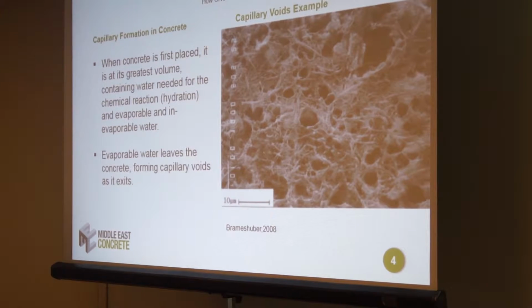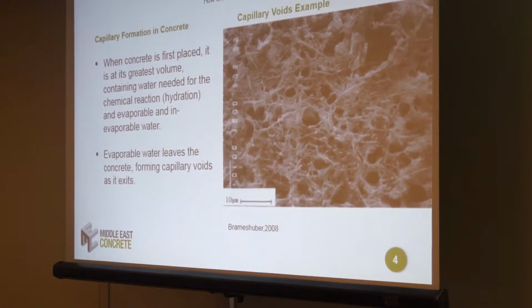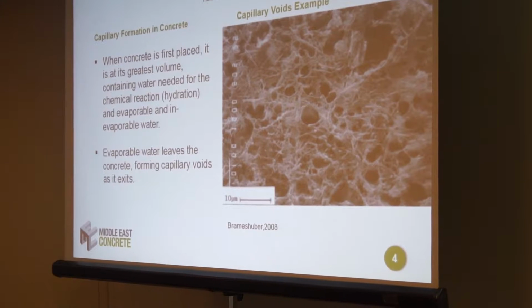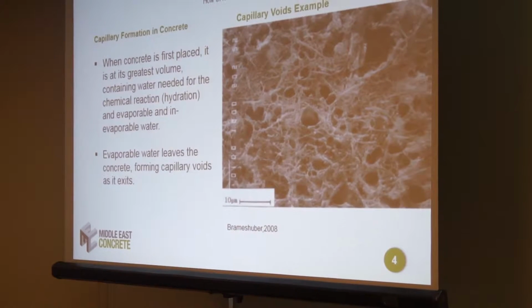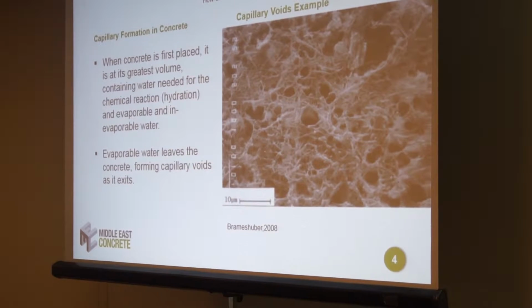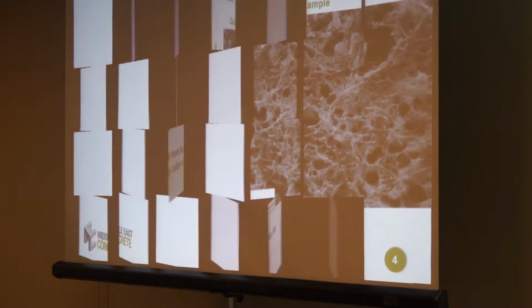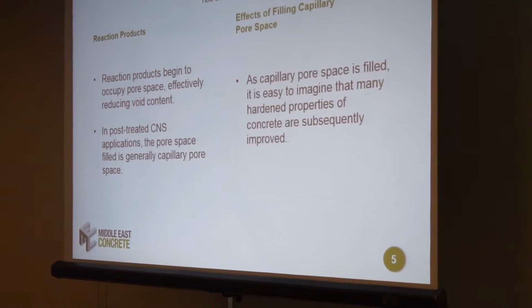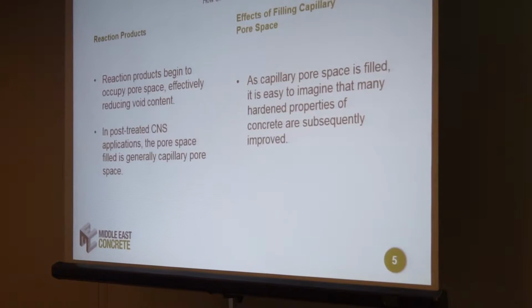So we know that when concrete is first placed, it's at its greatest volume most of the time. So you have water of convenience that's there above the water that's needed for the chemical reaction of hydration to take place. That water leaves, the evaporable water leaves the concrete, forming capillary voids, or capillary voids, as my Australian friends like to say. Those capillary voids are like little rivers that form as the water evaporates from the concrete. The problem is that those capillary voids are not only the way that water leaves, but they're also the way that water and other contaminants can enter the concrete.